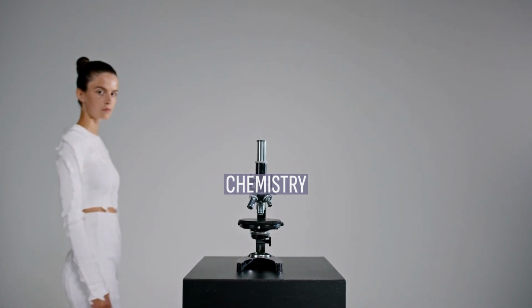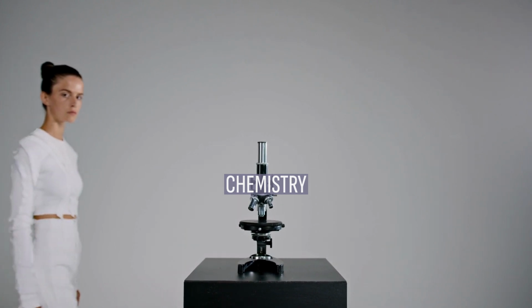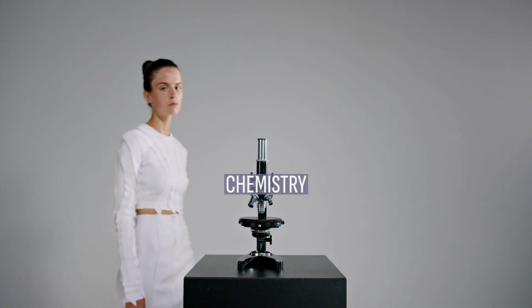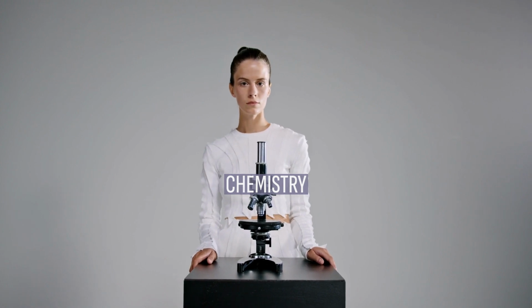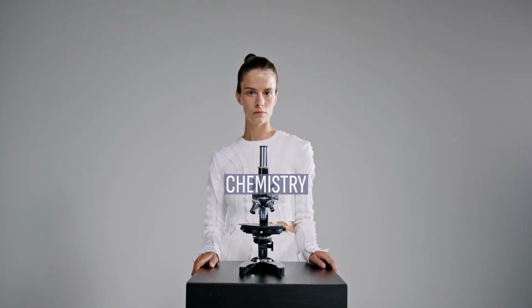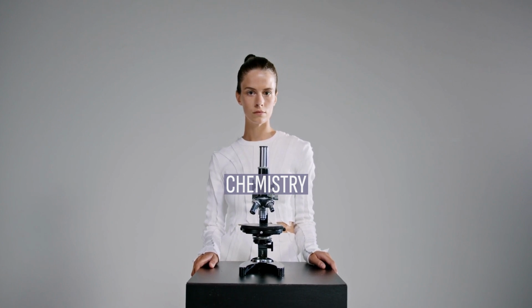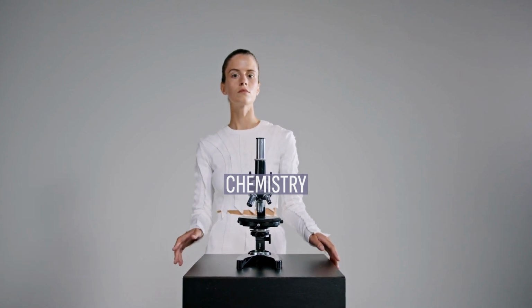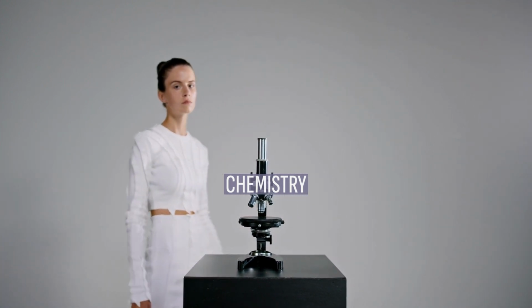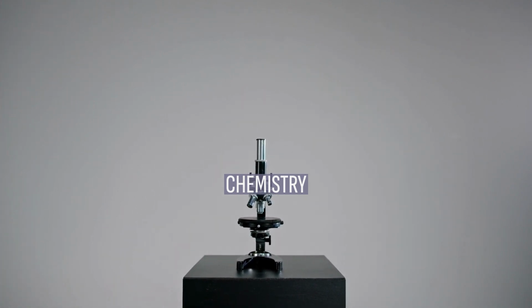As the current travels around the circuit, when the electrons enter the cathode carbon rod, they combine with manganese dioxide MnO2 and water H2O, which react with each other to produce manganese oxide MnO and negatively charged hydroxide ions. This is accompanied by a secondary acid-base reaction in which the hydroxide ions accept a proton H+ from the ammonium ions present in the ammonium chloride electrolyte to produce molecules of ammonia and water.